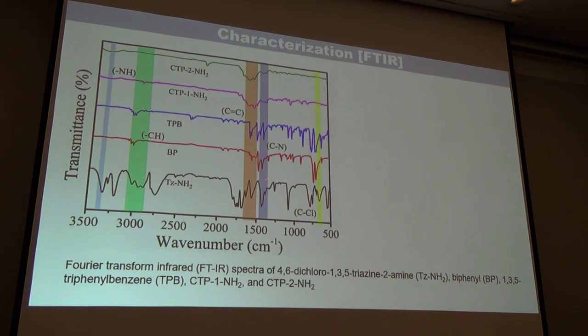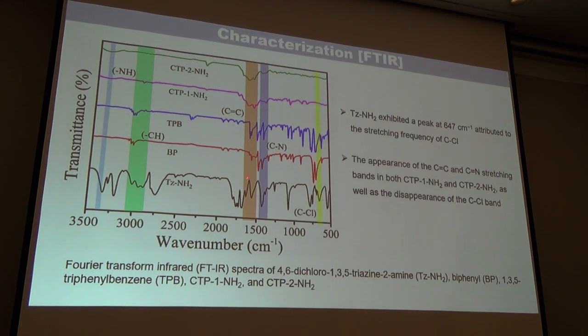The polymer material is characterized initially with FTIR analysis. As we can see here, the stretching frequencies for C=C, C-N, and C-H are present both in the monomer as well as in the polymer. Meanwhile, the stretching frequency of C-Cl at 647 in the monomer has disappeared in the polymer, which suggests that all these bonds have reacted and formed the polymer. So the synthesis is quite successful.